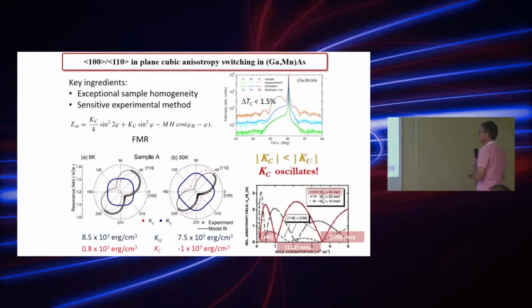Then the first experiment that we performed was FMR, and the results of our measurements done at 6 Kelvin and 50 Kelvin are summarized here, and the experimental points are these open circles. And it turned out to be possible to reproduce this experimental dependency very well, and to do this we needed one uniaxial term, this one in this expression, these red dots, and a cubic term, and the cubic term is this one. So at 6 Kelvin, this cubic term looked like this. At 50 Kelvin, it looked like that.